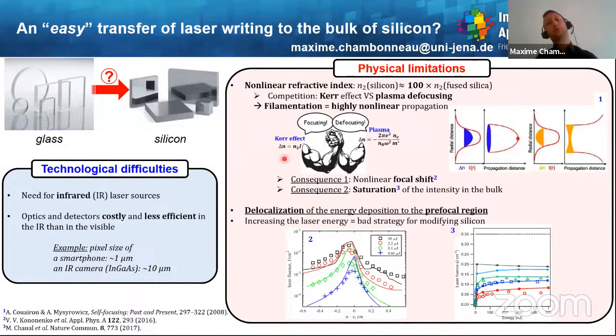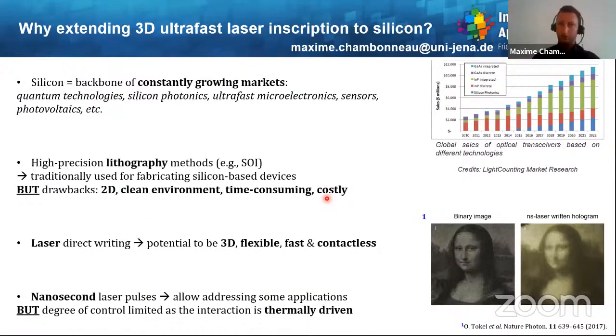And when you take those two consequences together, well, you can conclude that there is delocalization of the energy deposition to the prefocal region. And a consequence of this is that increasing the laser energy will be a bad strategy for hoping to modify silicon. So why should we aim at extending 3D ultrafast laser inscription to silicon?